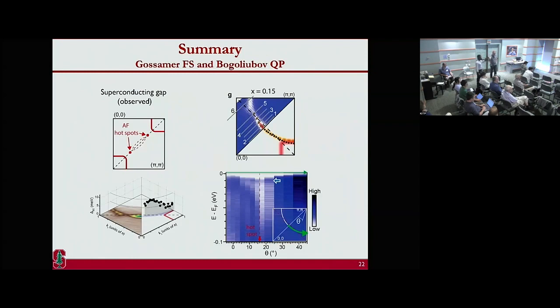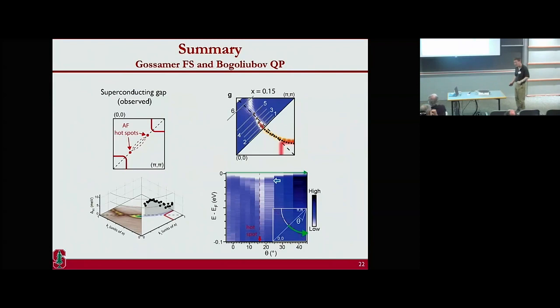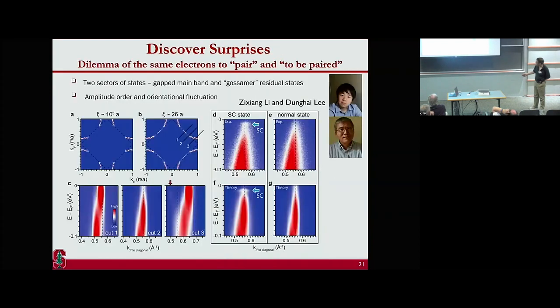Okay, Philip, I would say that one of the nice things about the electron-doped system is that the physics is non-monotonic. In the hole-doped system, this hotspot is very close to the antinode, and then many other things happen. Now it's so separated from the antinode, and you know this maximum corresponding to the antiferromagnetism, and this can give you an insight even into the so-called pseudogap phenomenon. For this pseudogap is clearly related with magnetic order. So if you show your main phase diagram again, at the beginning, yeah.